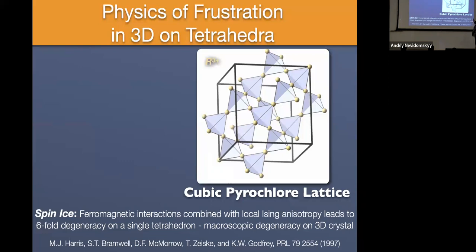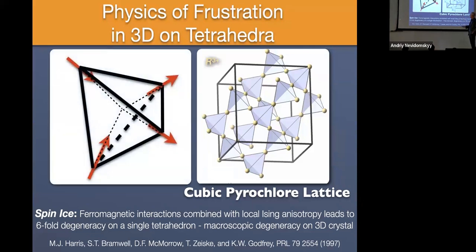And what's interesting, to me at least, about this family of materials is that they're cubic materials, and the local architecture of the material is a network of corner-sharing tetrahedra. So you've got a whole bunch of tetrahedra here with 4 sites at a vertex, and they're connected in a 3-dimensional array such that they fill all space. Okay. Now let's see what happens when we decorate the vertices of a single tetrahedron with magnetic dipole moments, and then give them certain properties in terms of their anisotropy and their interactions.